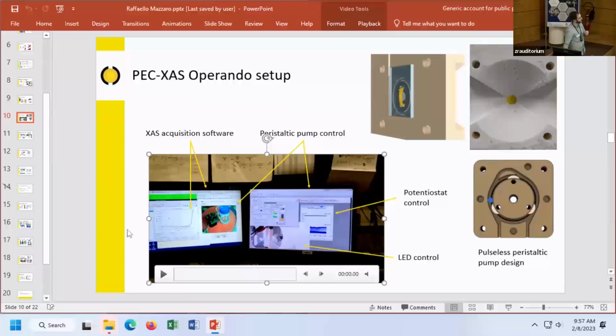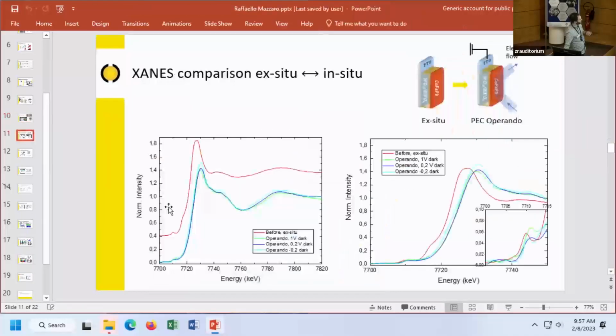And this is not what we desired, obviously. So one by one, I'm sorry, but it looks like... So getting to the XANES spectra, this is a comparison of the spectra of the same cobalt iron Prussian blue co-catalyst ex-situ with the one we got in the operando experiments. Don't mind for now about the potential, but basically you can already see here, just by stacking them, how that is changing a lot from the ex-situ to the operando measurement.